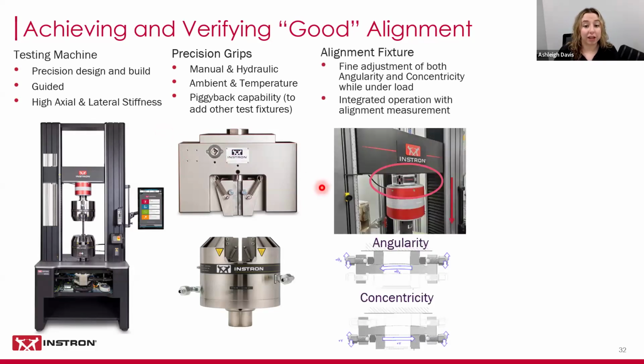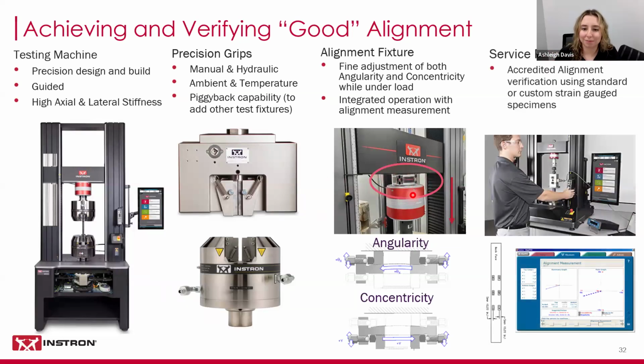We can introduce the alignment fixture. This is our Align Pro, which allows adjustments of the angularity and concentricity while under load. It sits in between the crosshead and the load cell. You essentially get it adjusted by service, and then you forget it. And that should be good for the year. This does pair with our service products, which includes the accredited alignment verification using standard or custom strain gauge specimens. So we can report out the bending moment in the load strings using that Align Pro software.